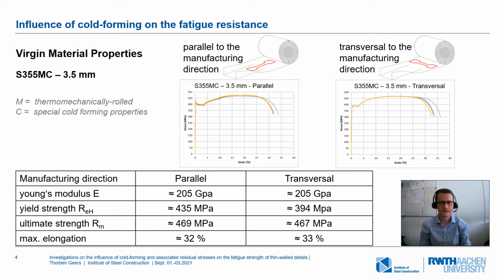With regard to the virgin material, we tested a lot of different material types and thicknesses, but in this presentation I would only like to present one single type of material because all of the other types and thicknesses don't vary that much in the values of the properties. So in this case, I have chosen the material as S355MC with a thickness of 3.5 millimeter. The M indicates the thermomechanically rolled material, and the C is the indication for special cold forming properties.